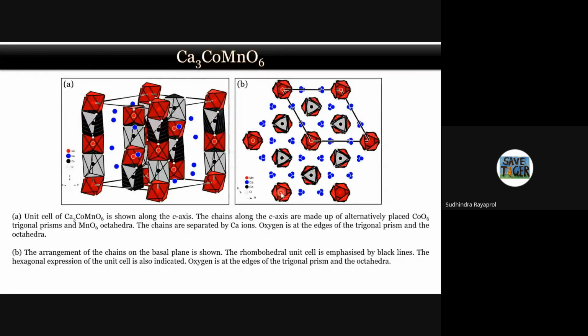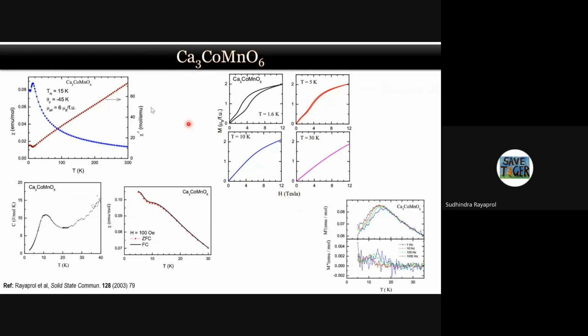Now coming to some examples, again going back to Ca3CoMnO6, we have seen that it has a geometrical structure. It has this kind of a frustrated ground state. It can have a frustrated ground state in the event that there is an antiferromagnetic ordering among the chains. So if you look at the magnetic susceptibility, this shows that it has an antiferromagnetic order, with a Neel temperature of over 15 Kelvin. If you look at the ratio of theta p to TN, it indicates that there is some kind of frustration already present in the system. Because if you calculate the frustration parameter, it comes out to be around 3.